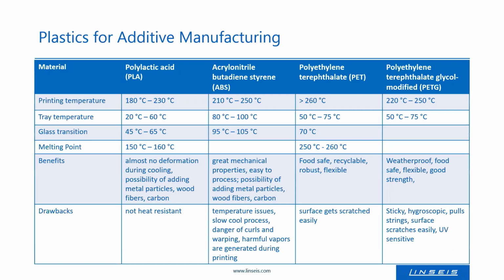PLA also offers the possibility to add metal particles, wood fibers, carbon, or similar to the filament. Another advantage of PLA is that it shows almost no deformation during cooling, which can also be enhanced by using a heated tray. The recommended temperature is 20 to 60 degrees Celsius. The drawback of PLA is that the printed object is not heat resistant, so the maximum use temperature for the object is up to 60 degrees Celsius.